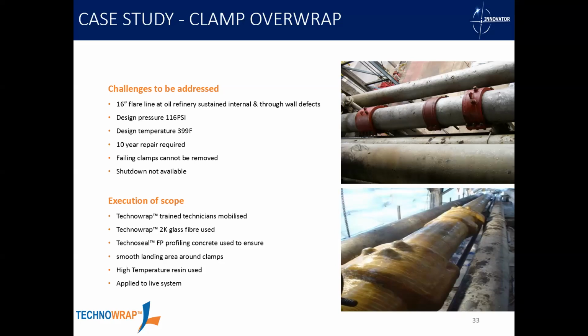So we then treated the clamps as defect areas. We applied the 10-year design life. So what we actually designed for was a clamp failing. And then, as you can see, we wrapped over the whole area. We achieved really good compression over those areas. You can actually see the bolts almost pushing through the composite there, such a good level of compression. And that was all applied live as well. So again, it meant they didn't need to do any sort of shutting down or anything.